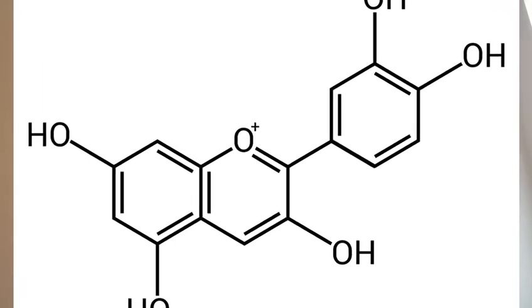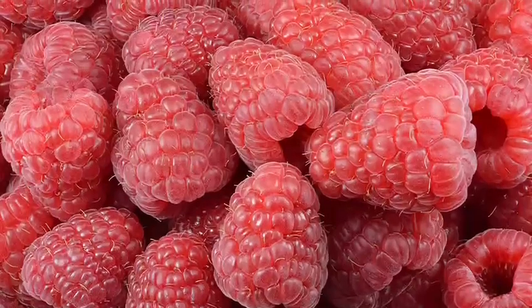In our lab at UChicago, we actually used anthocyanin, which is a dye molecule that can be commonly found in berries. So we used raspberry juice to create our solar panel. Obviously today, dye-sensitized solar cells are still a very new approach to absorbing solar energy, and not as efficient as silicon solar panels, but it is a very cheap and useful alternative to silicon solar panels, and that's why we're trying to research it.